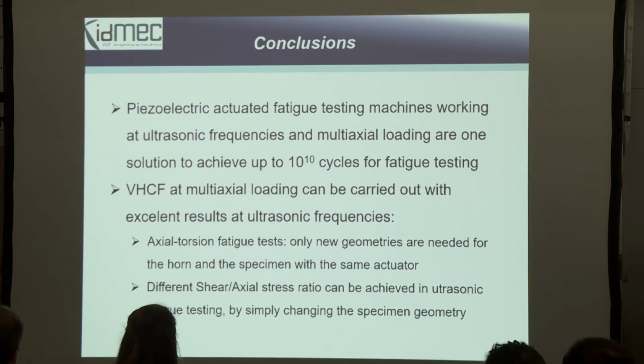And we have achieved different shear to axial stress ratios with ultrasound just by changing the specimen geometry.